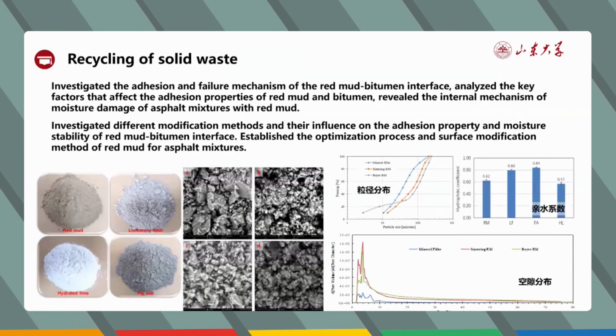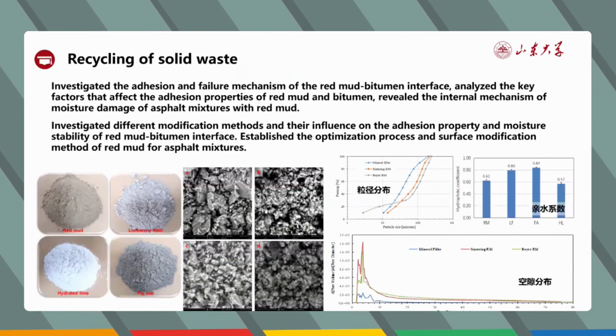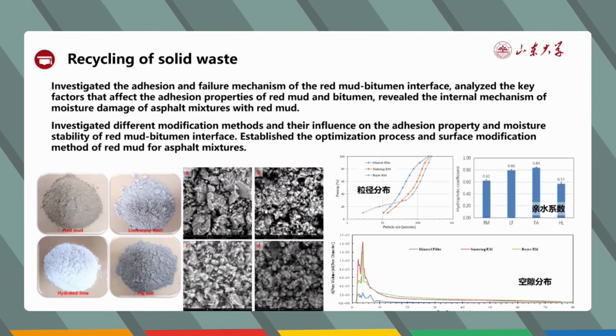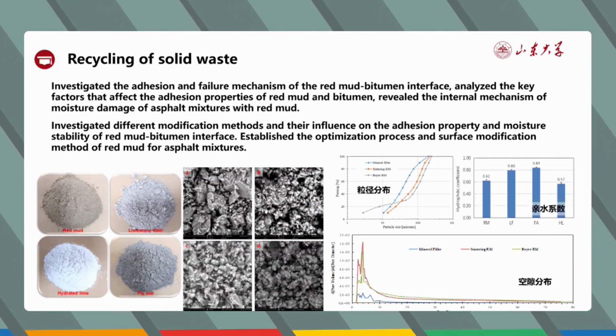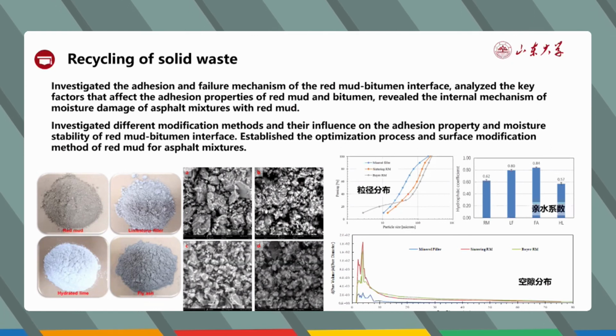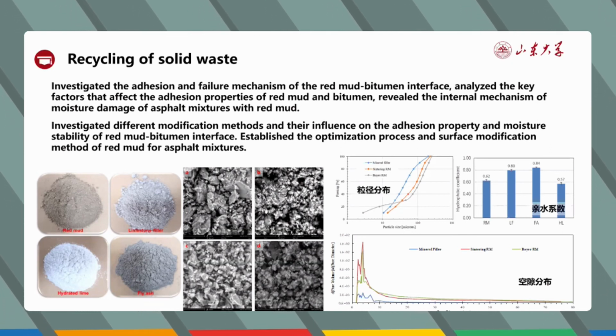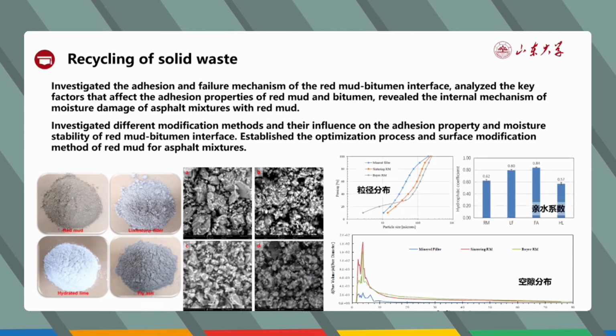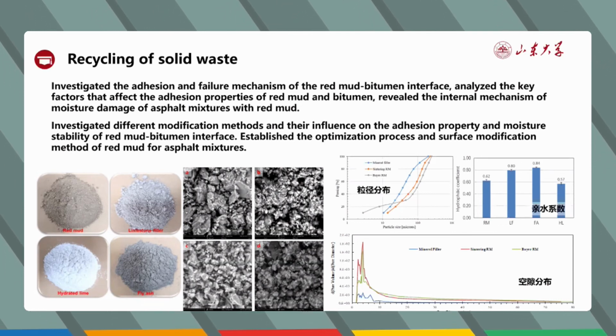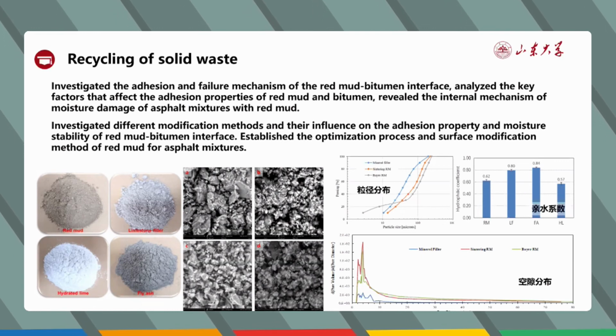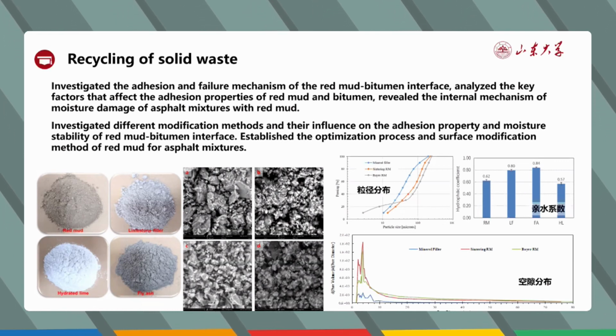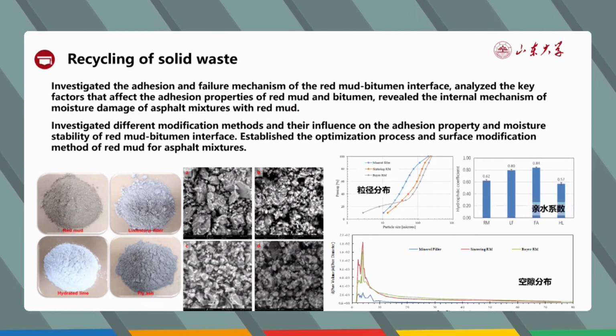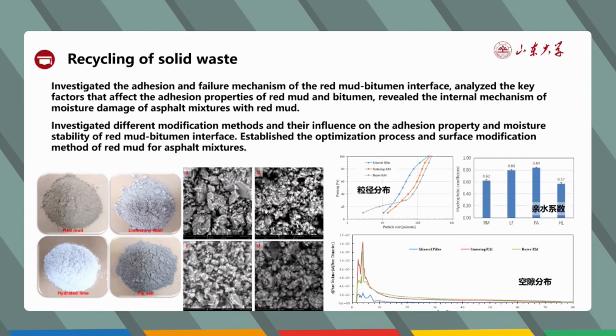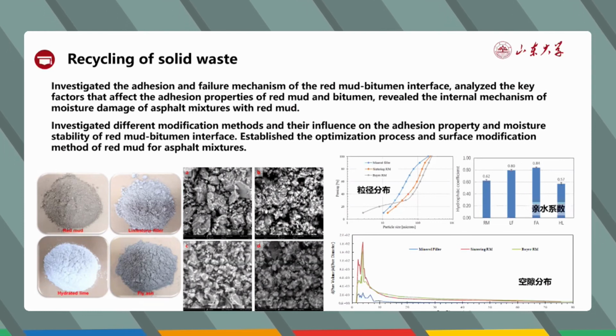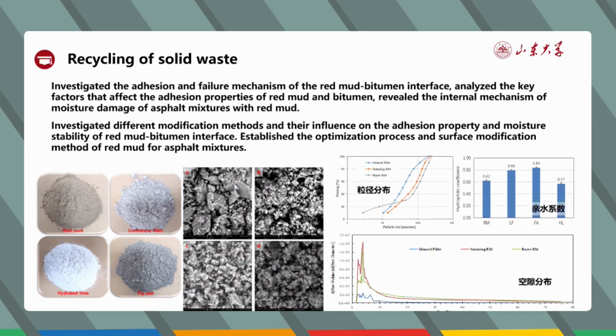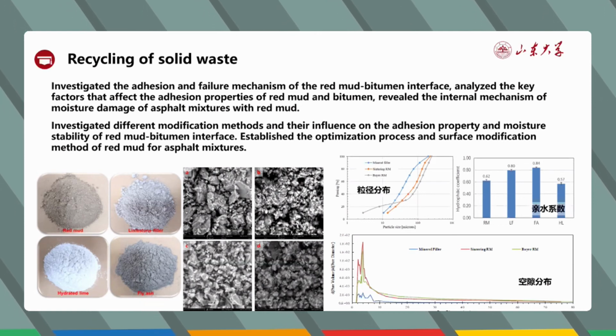The last part is recycling solid waste. Solid waste is a byproduct of some industries. This section will focus on the red mud. This is a byproduct obtained from aluminum production. In this part, we investigated the adhesion and failure mechanisms of the red mud bitumen interface. We also analyzed the key factors that affect the adhesion properties of red mud and bitumen, and revealed the internal mechanisms of moisture damage of asphalt mixtures with red mud.